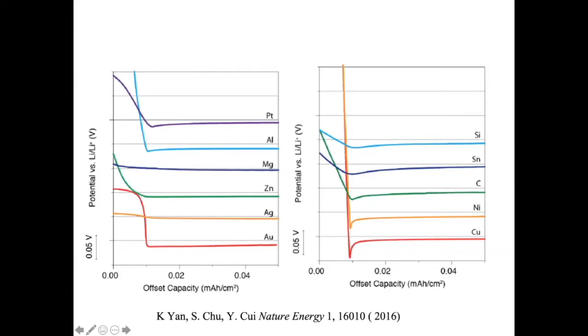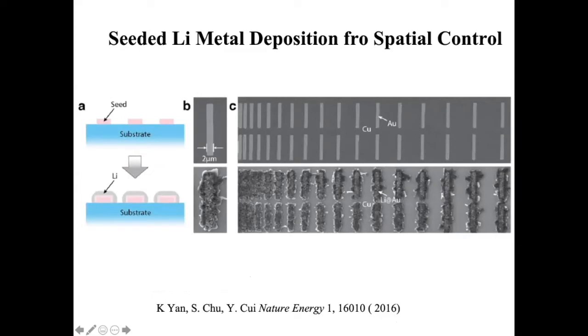So having this now allowed us, for the first time, to design an experiment to have spatial control of where lithium deposition will take place. This is an example of a gold pattern on copper. And you deposit lithium, you see lithium go onto gold, but not copper, because lithium has a nucleation barrier on copper. They don't really like copper. You can do this experiment going up to reasonable current density. Of course, if you drive it too hard with high current, then the overpotential is too much. You are going to have deposition everywhere.